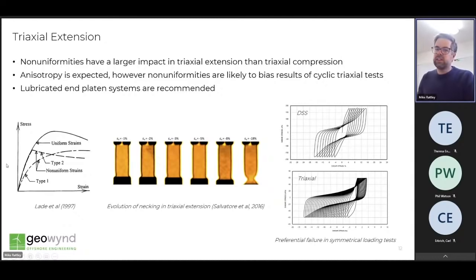Since we normally want to investigate the symmetrical loading conditions, that's the two-way loading case that Carl referenced, where deviatoric stress is applied in both compression and extension in a triaxial sense, this can actually distort the rate of strain accumulations in the extension condition, leading to a sort of preferential failure in that condition. And non-uniformities can be significantly reduced through use of lubricated end platens, and these can be tricky to implement in practice, but they are recommended in cases where significant cyclic stresses are to be applied in triaxial extension. So that's another method to be aware of to reduce the impact of non-uniformity in testing.